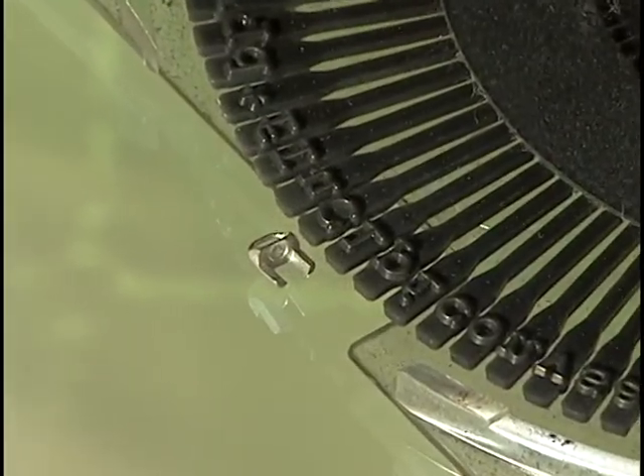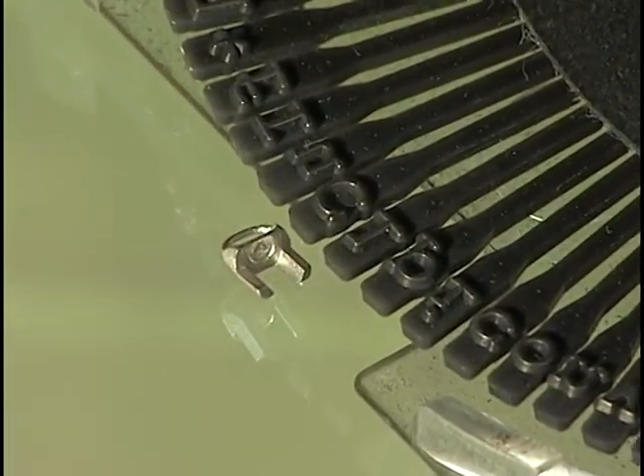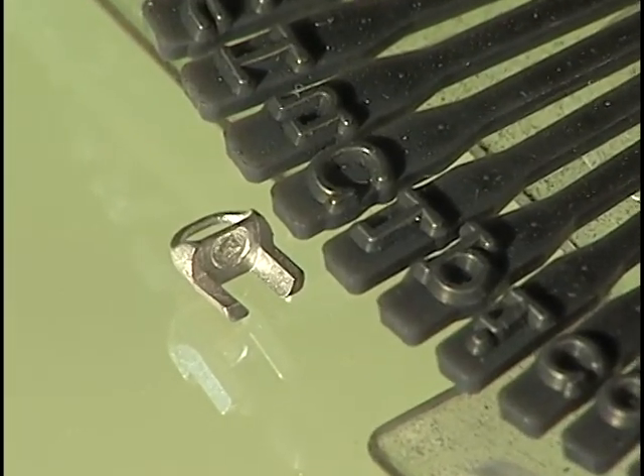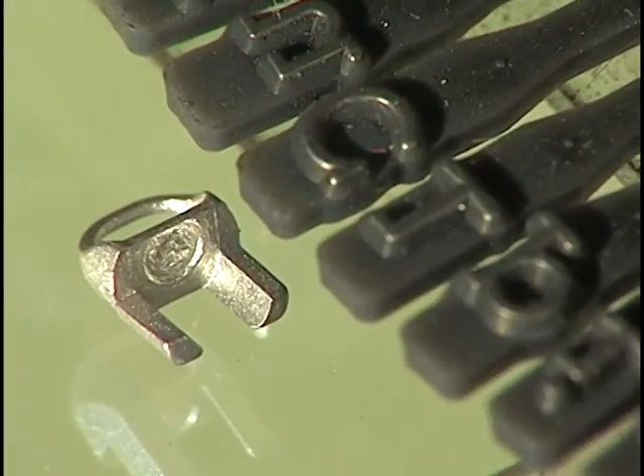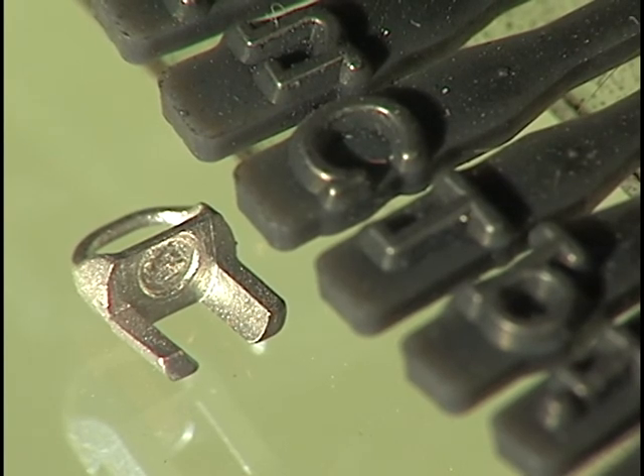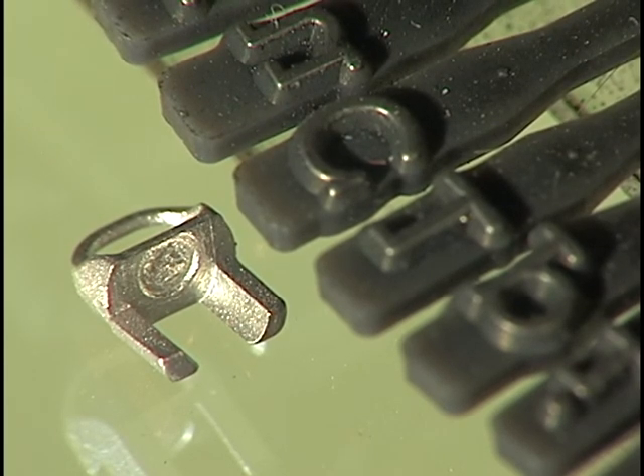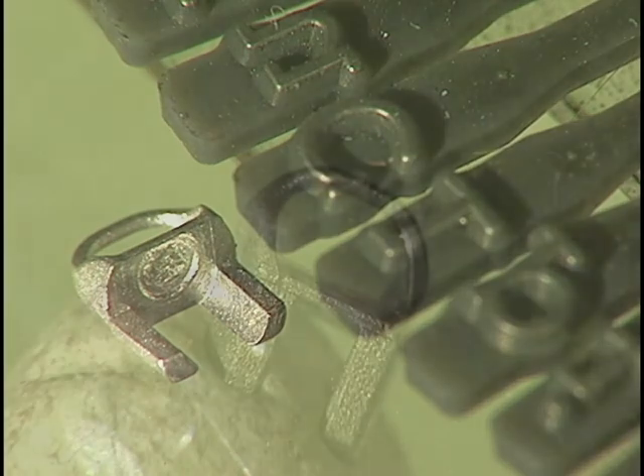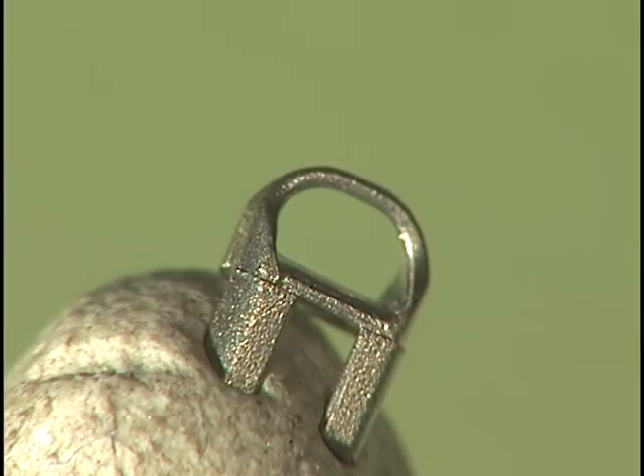Made close to a net shape, the MIM pin has a typical density of 7.85 grams per cubic centimeter, a tensile strength of 78,000 psi, and yield strength of 29,000 psi. Metal injection molding replaced an assembly made by wire EDMing 3 parts and assembling them to each other by laser welding. Choosing the single MIM parts reduced the customer's final assembly time by 2/3, from 15 minutes to just 5 minutes per unit.